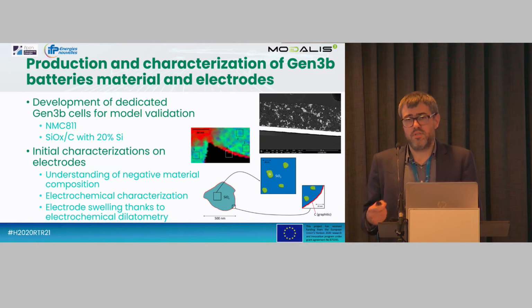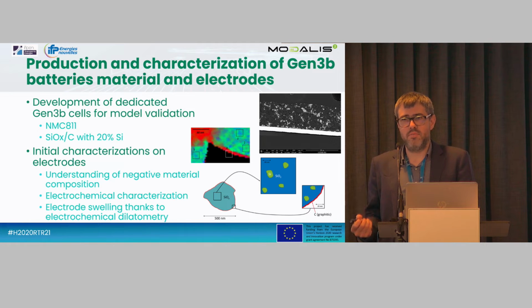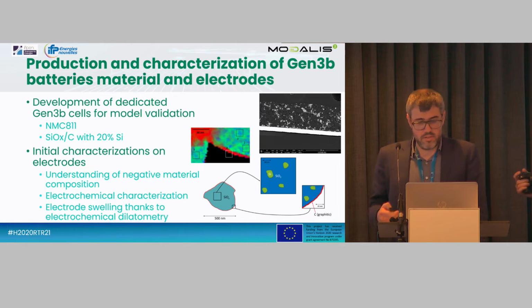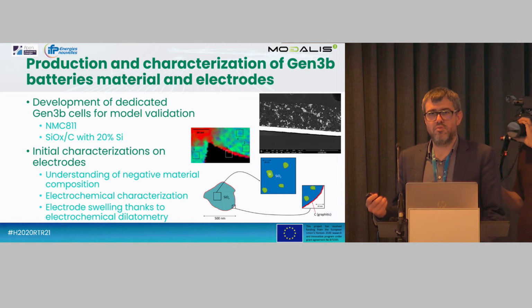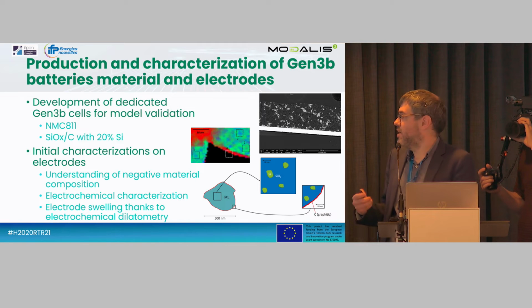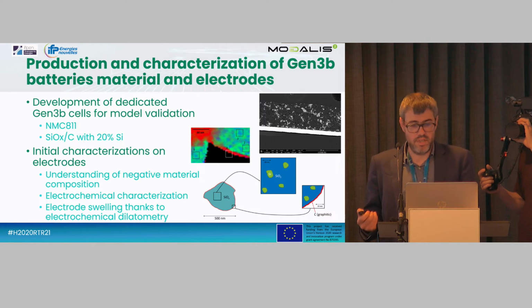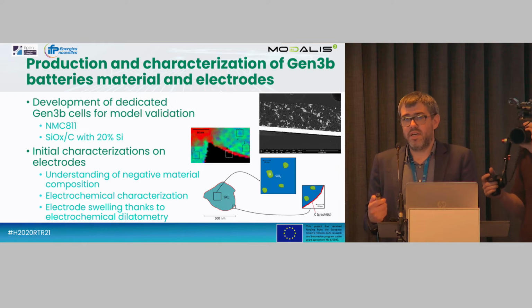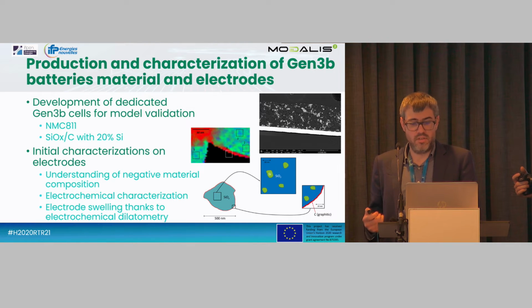So the positive material was, as I said, given by Umicore. The negative material was a commercial one, so we needed to characterize it. So we did specific characterization using SEM and TEM, and this allowed us to understand what was composing this material, especially with silicon inclusion into a silica matrix and embedded into a graphite layer. Thanks to that, it was possible to send them to the other teams in order to create a dedicated modeling of this material in order to understand or to predict its behavior. We also did the electrochemical characterization and specific swelling measurements using an electrochemical dilatometer in order to understand the swelling of the complete electrode when it's implemented into an electrode.